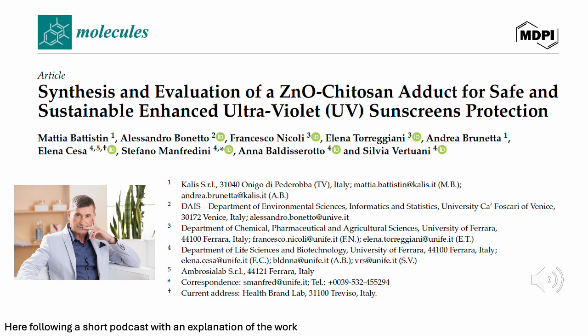Okay. And the difference was huge. The ZnO@CS showed a dramatically reduced ability to break down the dye compared to the plain zinc oxide. Like after the UV exposure, over 50% of the dye had degraded in the presence of plain zinc oxide. Wow. But with the ZnO@CS, less than 1% of the dye was degraded. That's incredible. So basically, the chitosan was acting like a shield, preventing the zinc oxide from going haywire and creating all those reactive oxygen species. Exactly. It really seemed to be effectively blocking that photocatalytic activity.